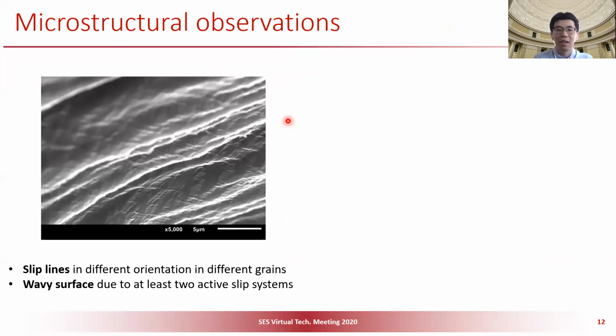Okay, and our experimental results get more validation from the microstructure observations, which are really interesting to us. For example, we observe a lot of slip lines on the surface of the sample, and in each grain there are different slip lines in different orientations. That means there are at least 2 active slip systems, and as a result, there will be a lot of waves on the surface. So a wavy surface is observed in almost all the tensile tests.